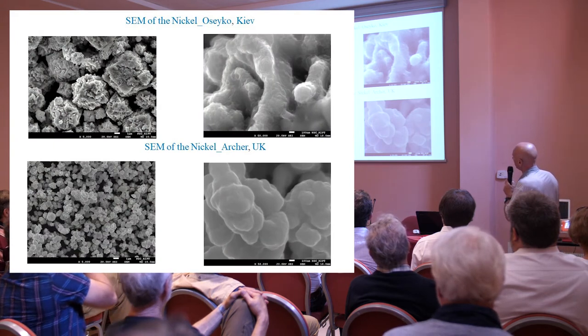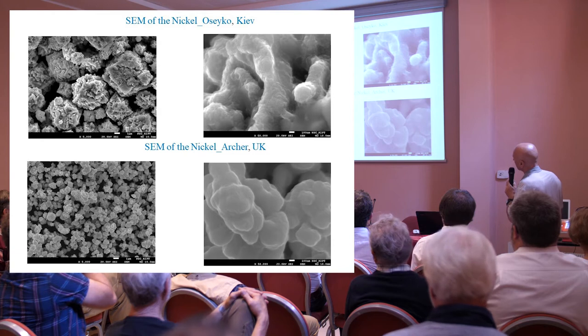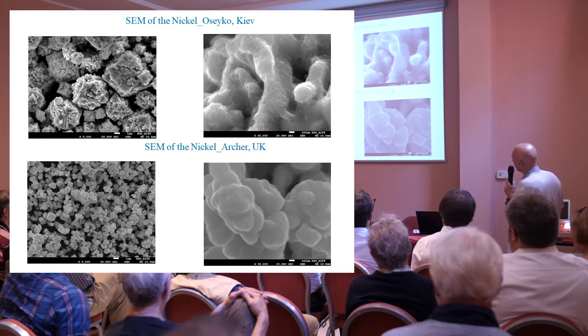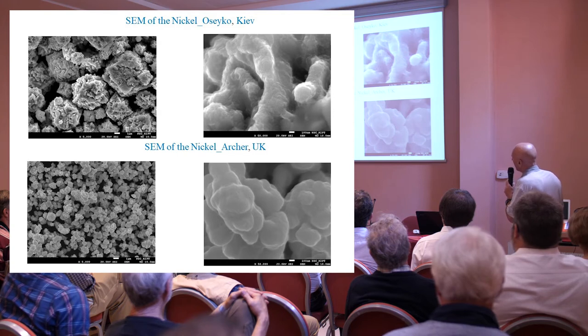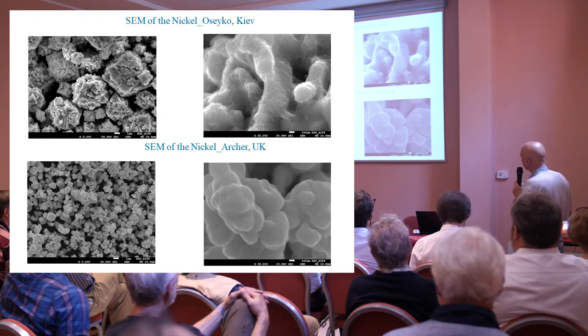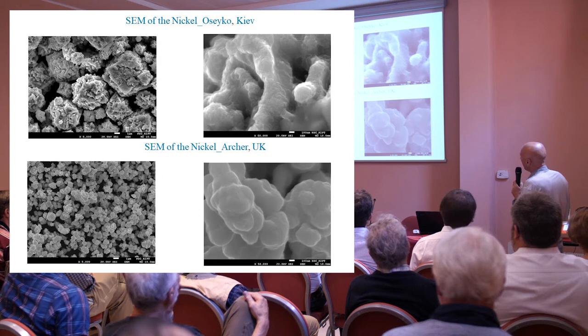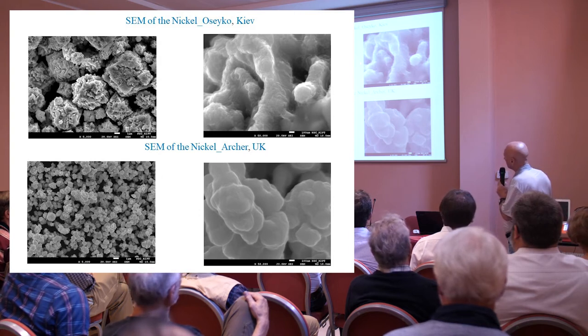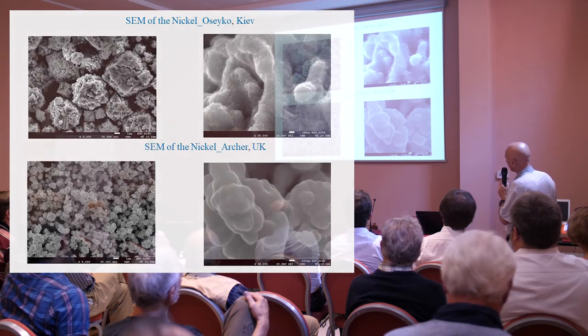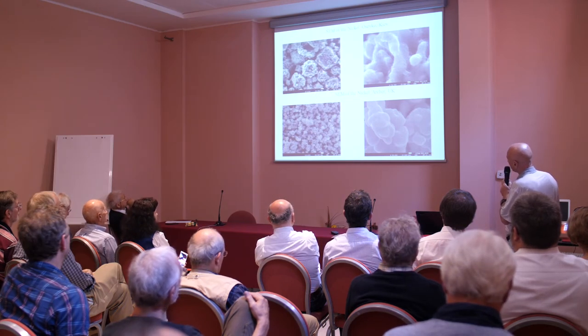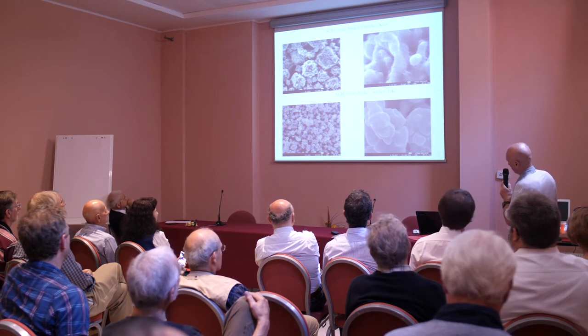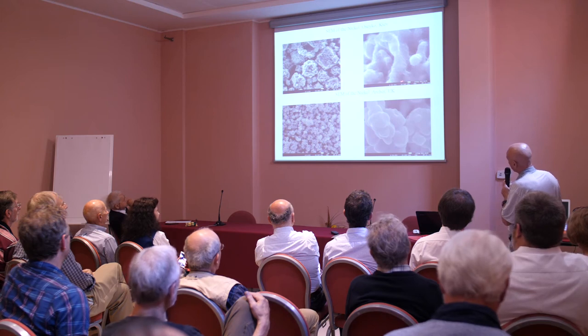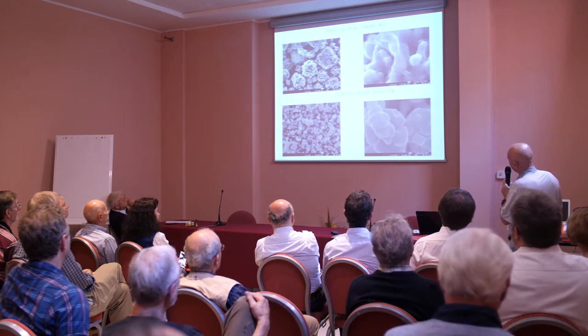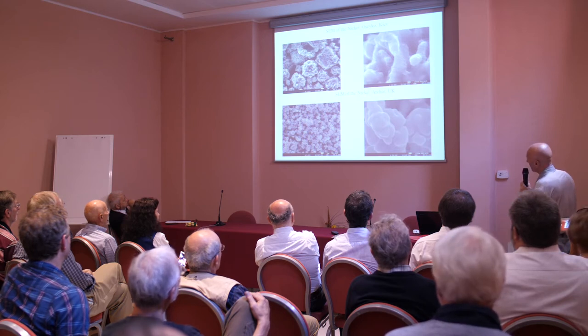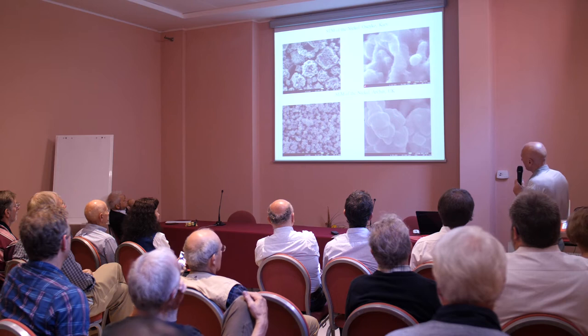Okay, that's how the specimen looked in the scanning electron microscope. We tried two brands so far of nickel. This I call nickel Oseyko, because it's the name of the nickel Oseyko actually. And we actually don't know the method in which this powder was produced, but we see that it has a very well developed surface of the order of 100 nanometers. And another one, provided by Alan Smith from UK, this is a nickel Archer.